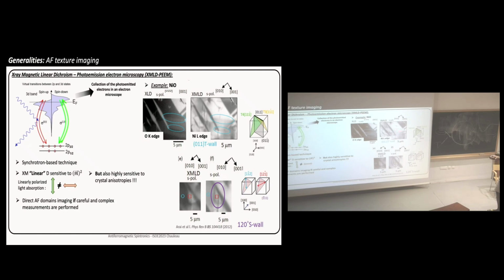And the nice thing is that, for example, it's very tiny, but here they managed to identify some T domains, as I discussed at the beginning. And here, also doing a very careful analysis for different incidences of light, they managed to identify some S domains. So this is another possibility.